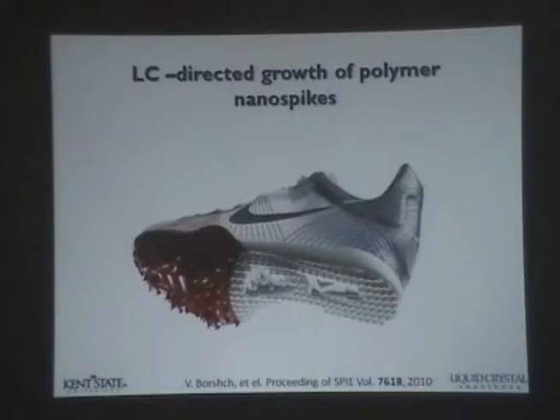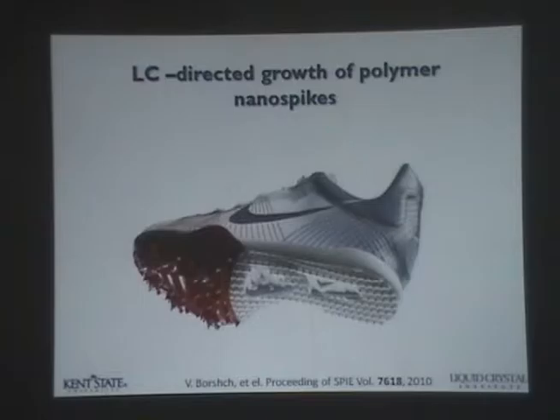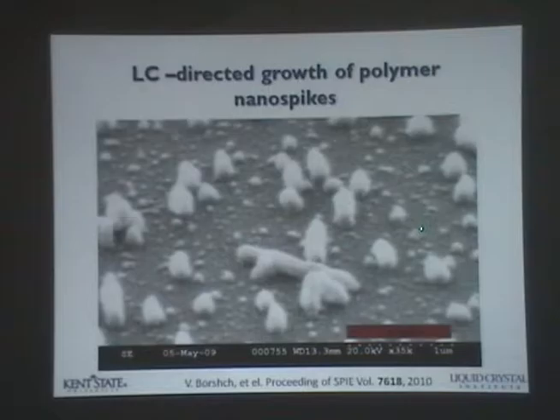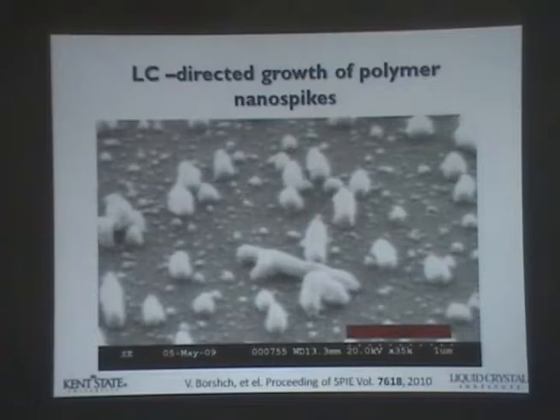In our lab we try multiple methods. After making this, we have polyimide on the substrate surface. Why do you need the spikes? If you are a good football player — they want to run fast and maneuver past defenders — they need shoes with spikes, because that gives you anchors on the grass. Spikes are like that. On the polyimide surface, we also create all kinds of spikes that are high and low, though not very uniform. The density depends on the polymer concentration initially. The diameter of the spike is roughly around 100 nanometers, with a scale bar of about 1 micron.